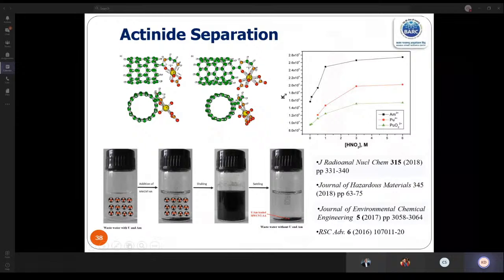Similarly in actinides, here we can functionalize carbon nanotube. It's called the amidoamine group. Theoretical studies were done, and then practically, in this bottle, this water contains uranium as well as americium, and these functionalized carbon nanotube powders were added, they were shaken, and when you allow them to settle, this water is free from them. So basically, carbon nanotube can be functionalized with another group called amidoamine, which is specific to the actinides. So in this way, I want to say that carbon nanotubes can be used for separation of target specific metal ions.